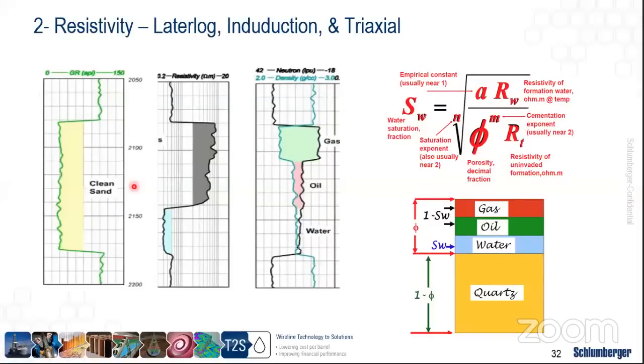So by just doing this quick look evaluation, we can start punching the numbers into the basic saturation equation, which is typically Archie's equation. So Archie's equation is SW, which is saturation of water, equal to the nth root of A, which is the empirical constant, typically assumed as 1, multiplied by RW, which represents the resistivity of water at a measured temperature downhole. And then it's divided by phi raised to the power of m, which is the porosity of the reservoir raised to the cementation exponent that's usually estimated or assumed as 2. And then we have RT, that's the deep resistivity that we can directly get from the tools itself, whether it's AT90 in case of induction, or RV in case of thin bed laminations, or RLA5 in case of laterolog.